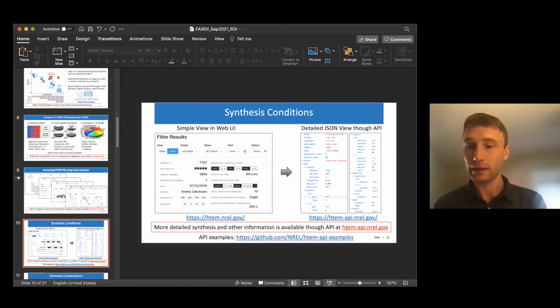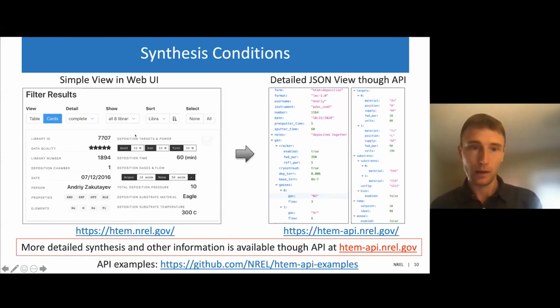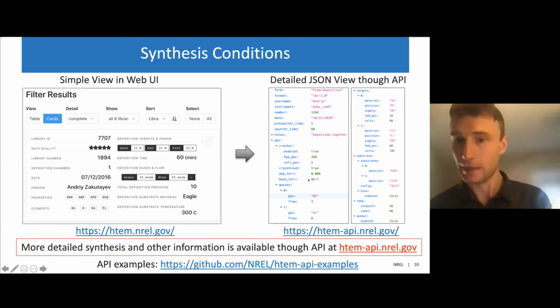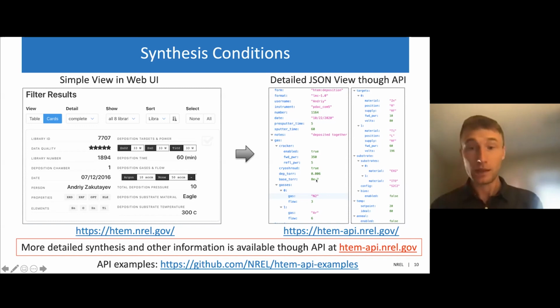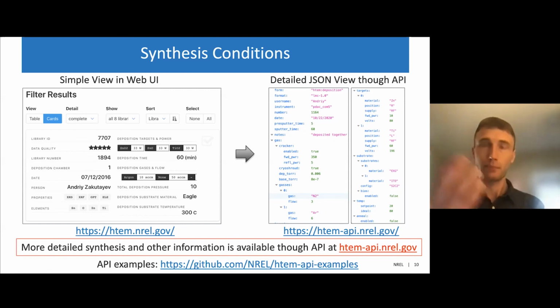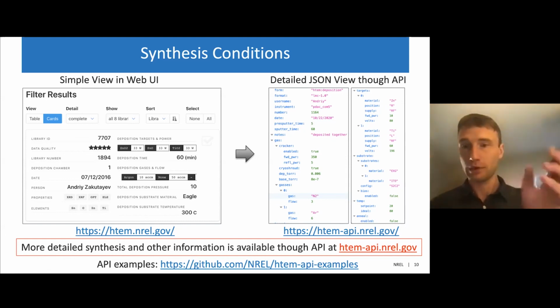But there are types of data in our database, accessible through the API, that may let you get an idea about how at least the relative amount of contaminants or hydrogen is changing between different samples. So for example, not in this web UI, but if you dig deeper into the API, there is a field under the gases called base_torr. This is the base pressure in torr of our chamber. For this particular sample, it happens to be 8 × 10⁻⁷ torr. That base pressure is pretty much entirely made out of water. And I think water, or cracking of water in plasma to produce some oxygen or hydrogen that can both intentionally or unintentionally be incorporated into the sample, is the main source of hydrogen.